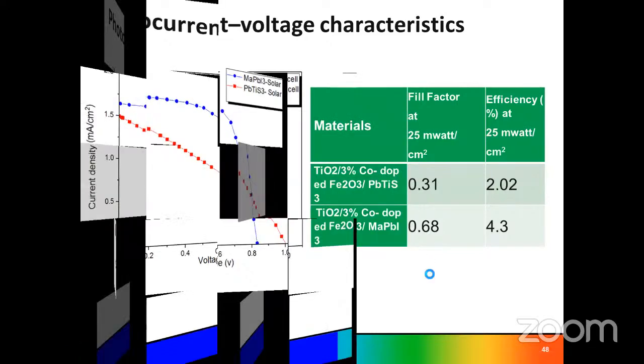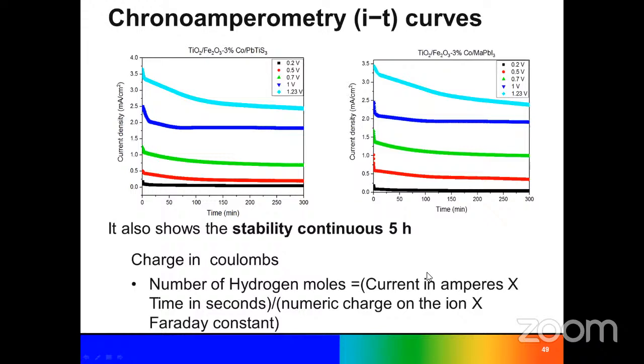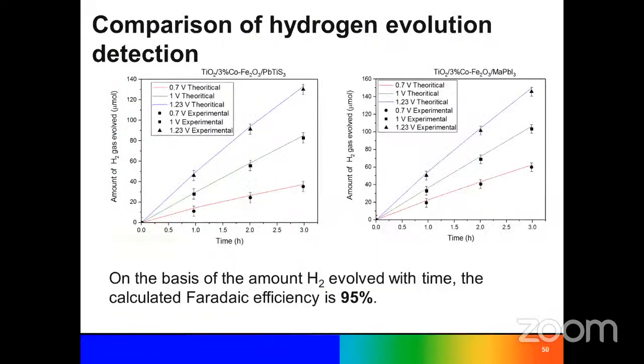Then we applied this material for a stability study, where we get more or less 5 hours of stability. In the case of the perovskite material, after half an hour the cationic site, particularly methylammonium, degrades and comes into the structure, and that creates the deterioration of the structure. That is the reason for the degradation of perovskite materials. So in this case, we got stability of around 5 hours.